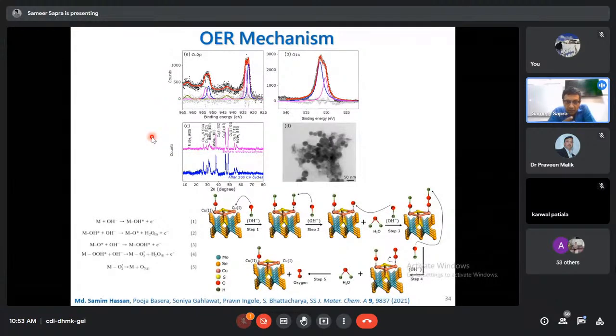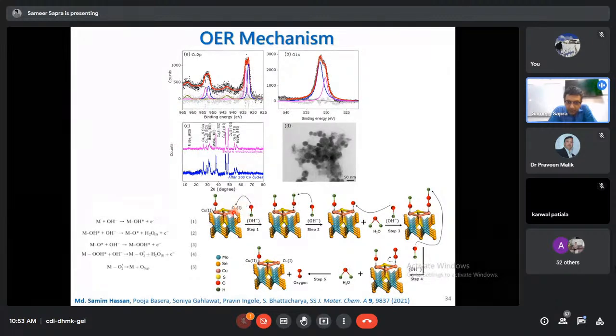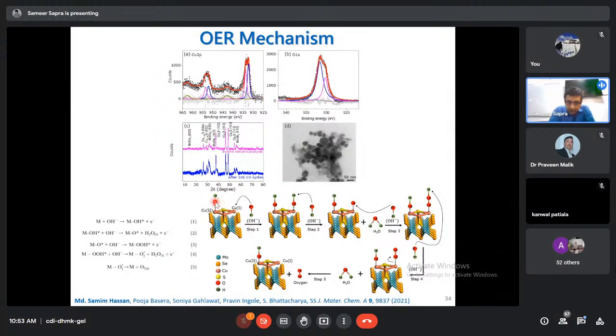If you look at panel A over here, copper 2p earlier had only one environment, but now it has two environments, one because of copper plus and one because of copper 2 plus. Okay, one is more oxidized, and that allows us to postulate a mechanism over here that we have copper 2 plus, we have copper 1 plus. The hydroxide goes over and attaches to this copper 1 site. The copper 2 is already passivated for some reason. But once the hydroxide goes off from copper 2, that also becomes copper 1 and can participate in the catalysis activity.